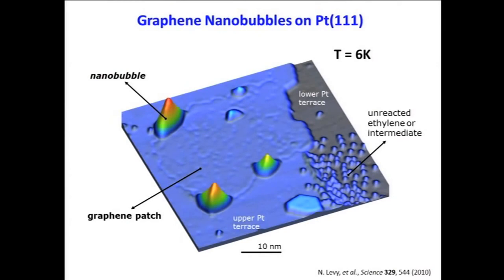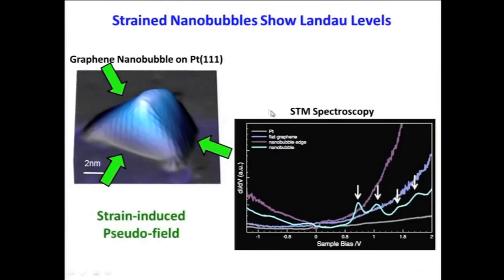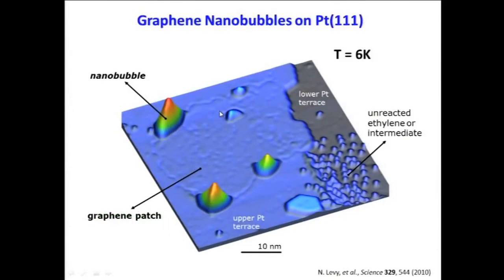This is what we saw. This is an STM image of graphene grown on platinum 111. This region right here is a patch of graphene, if you can see the outline of it. And these bubbles, which appear at nanometer length scale, we refer to as nanobubbles. We saw these nanobubbles all over the place on the graphene that we grew on platinum. And these nanobubbles have a triangular shape. They're like little pyramids with three sides, sort of tetrahedral.